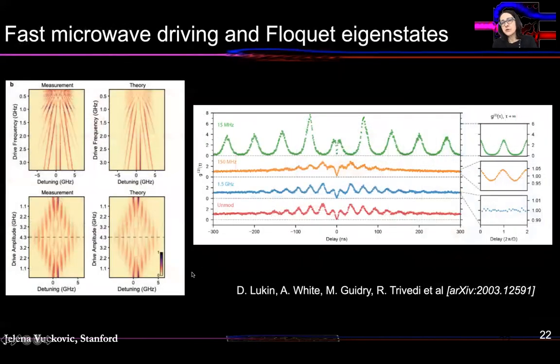Apart from DC Stark shift tuning, we have also recently demonstrated that if you tune with high-speed microwave signals that are faster than the decay time of the emitters inside of these color centers, you can achieve the regime of generation of beautiful Floquet eigenstates. And instead of seeing just two lines in the spectrum, as you would see under slow tuning, you will see this spectrum of lines, which are basically eigenstates of the periodically driven Hamiltonian. And from the time resolved measurements, we also proved that we're performing experiments on a single color center in this case.